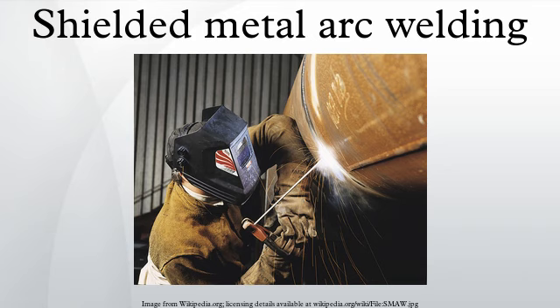Common electrodes include the E6010, a fast freeze, all-position electrode with a minimum tensile strength of 60 ksi which is operated using DCEP. E6011 is similar except its flux coating allows it to be used with alternating current in addition to DCEP. E7024 is a fast fill electrode, used primarily to make flat or horizontal welds using AC, DCEN, or DCEP. Examples of fill-freeze electrodes are the E6012, E6013, and E7014, all of which provide a compromise between fast welding speeds and all-position welding.